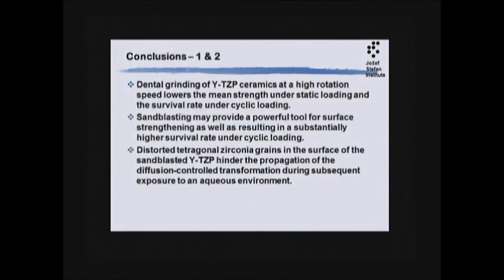Okay, we can summarize that part. Grinding and sandblasting exert a counteracting effect on the strength and survival under static, and also on the survival rate under cyclic loading. Sandblasting is not bad, but it depends how it is done. And the distorted tetragonal zirconia on the sandblasted specimens hinders the aging. How much, what is the practical result of this, we'll have to check. We don't know yet.